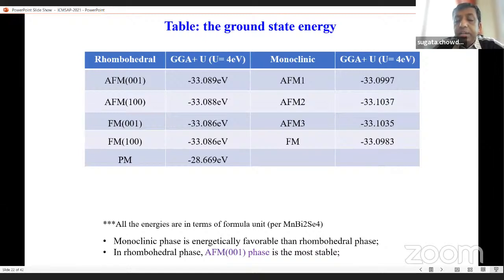And in the rhombohedral phase, the antiferromagnetic phase with magnetic moment out of plane, along the z direction, he also found to be the energetic ground state, which matches our result.